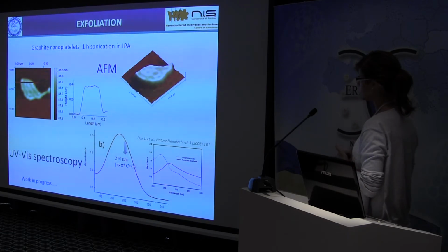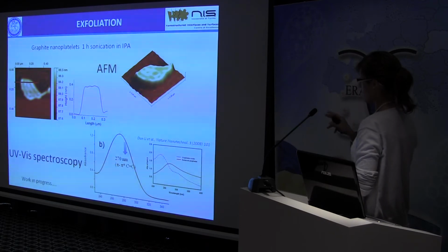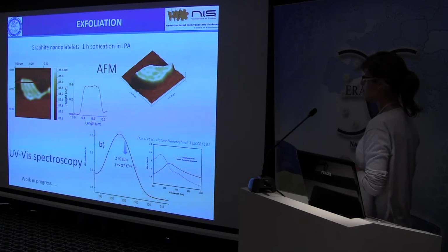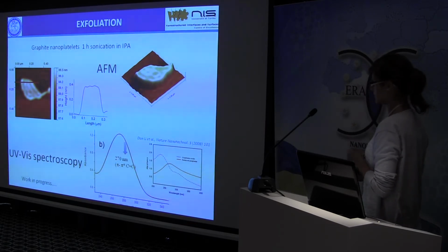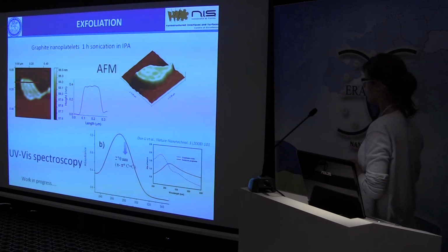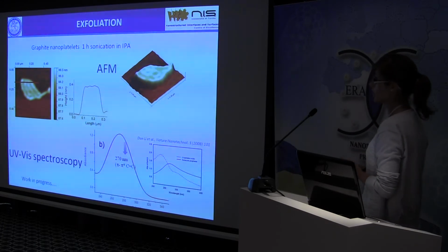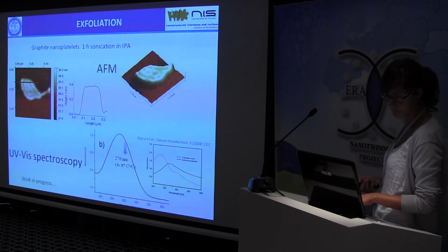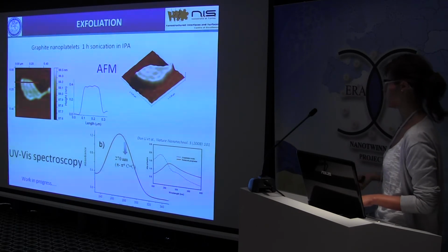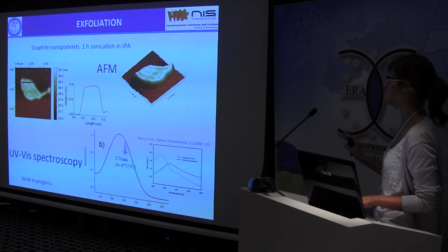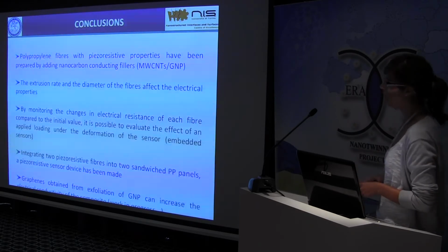Then the same dispersion was analyzed by UV-visible spectroscopy, and we have a band at 270 nanometers, which is due to pi-pi star transitions of conjugated carbon bonds. This value is very close to the value we found in literature for synthesized graphene. But this work is still in progress. This is all we have done about exfoliation of graphene. So, conclusions.